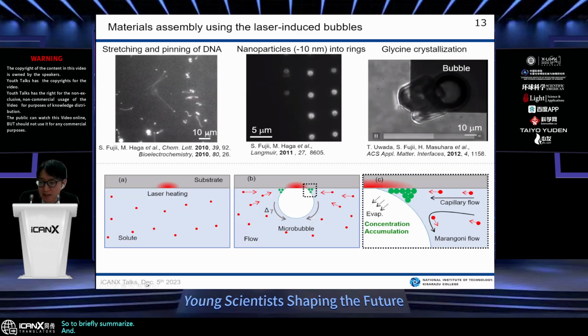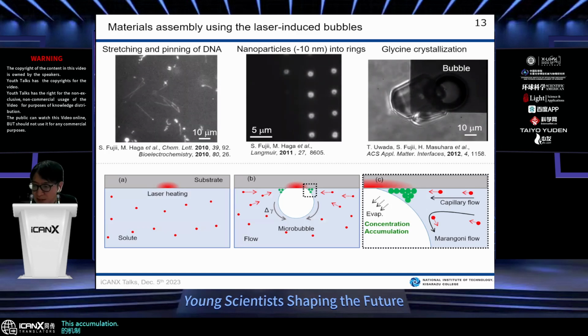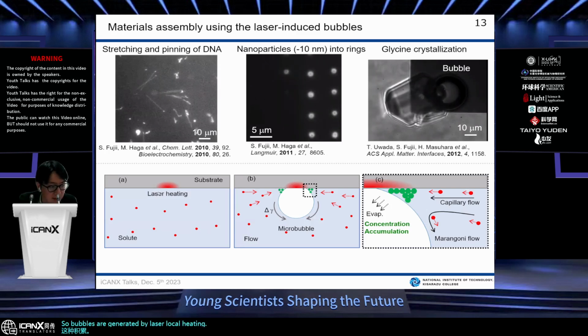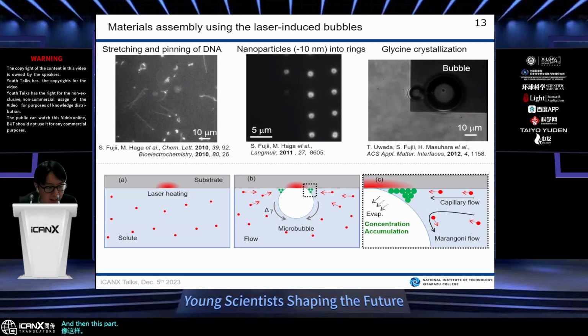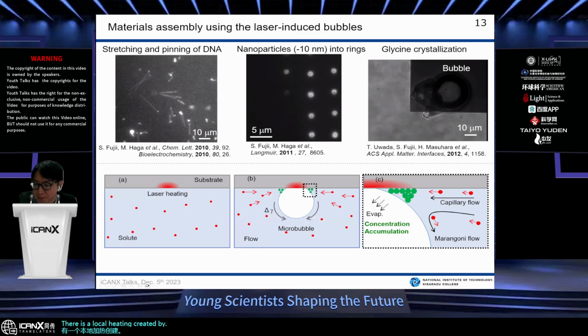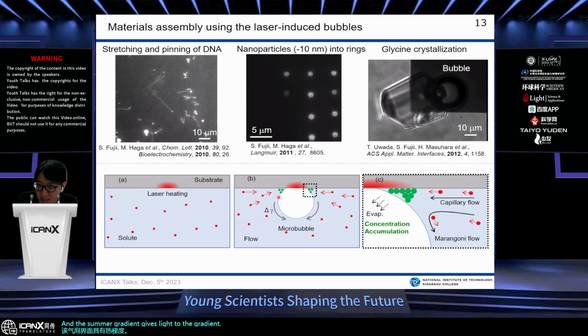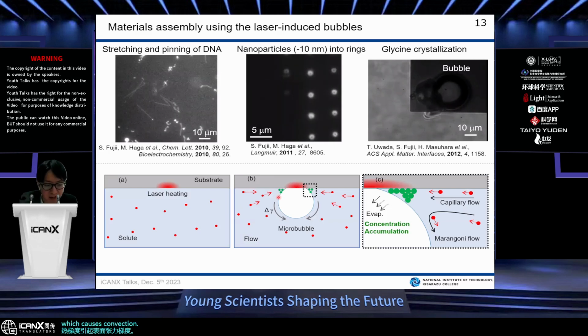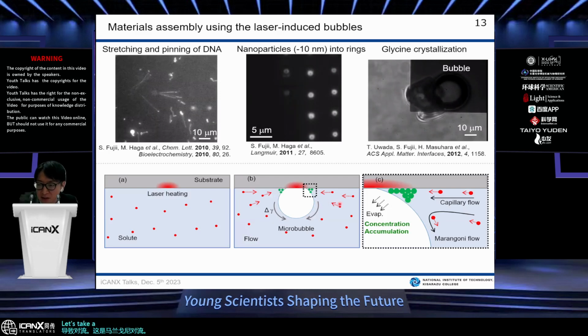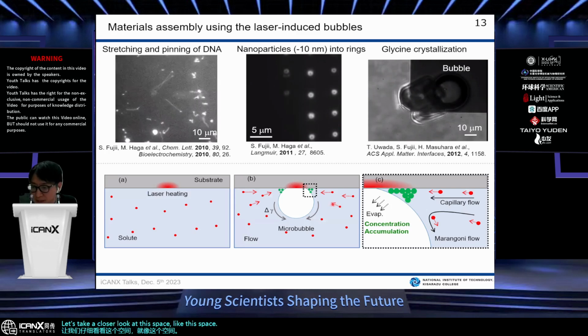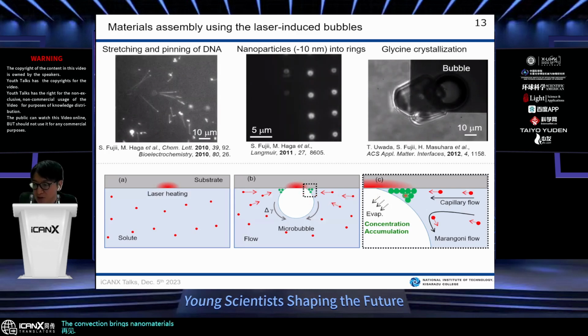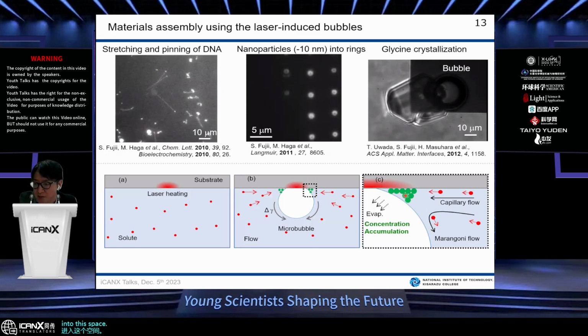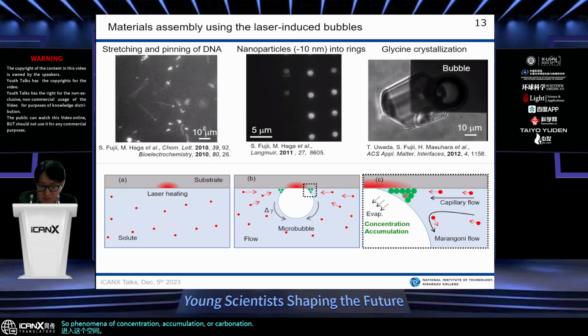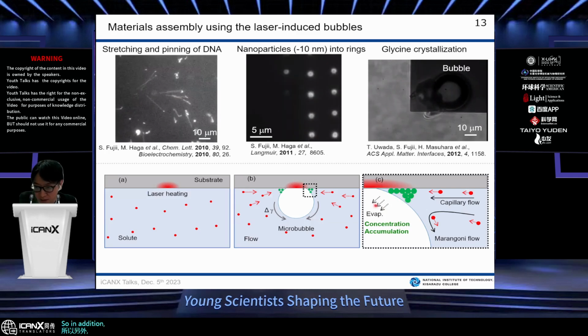And so to briefly summarize the mechanism of this accumulation, bubbles are generated by laser local heating like this. This bubble interface has a thermal gradient, and the thermal gradient gives rise to a gradient in surface tension, which causes convection. So this is Marangoni convection. Let's take a closer look at this space. The convection brings nanomaterials and molecular solutes into this space, so the phenomenon of concentration accumulation occurs here. In addition, this bubble interface disappears when stopping laser irradiation.